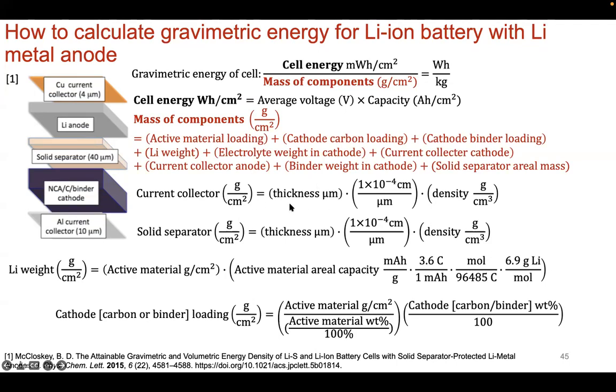So if you have the thickness of your current collector and its density, copper or aluminum, you can calculate out the grams per centimeter squared that way. The solid separator, similarly, the thickness that you put in, you then multiply that by the density of the material to get the mass. The amount of lithium converted to grams per centimeter squared is done here. And then similarly, the amount of carbon or binder that's in your cathode, you can also calculate by just the weight percent that is used.